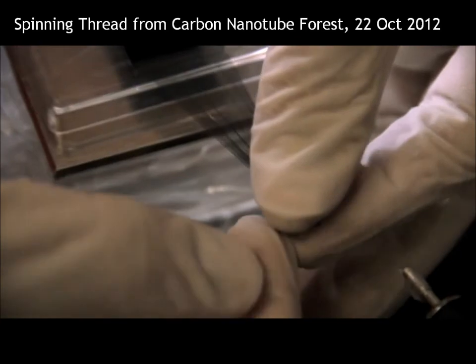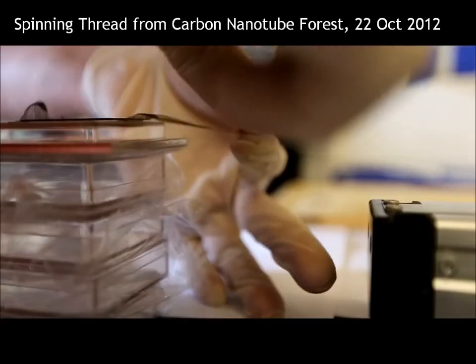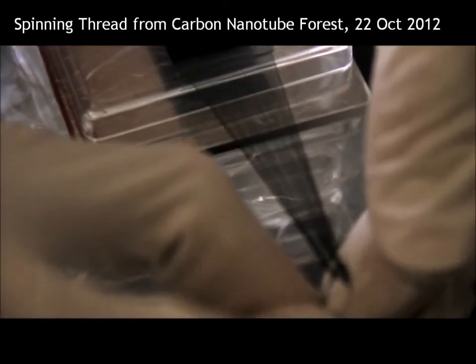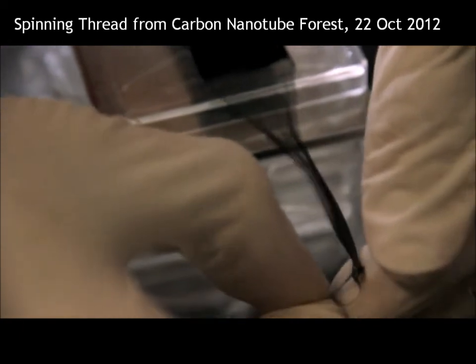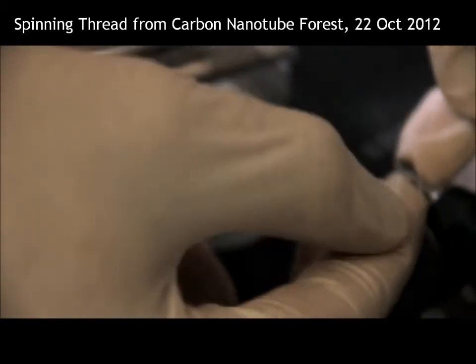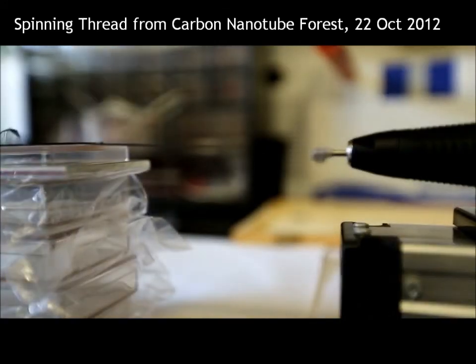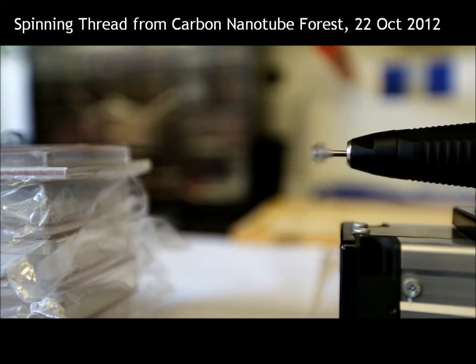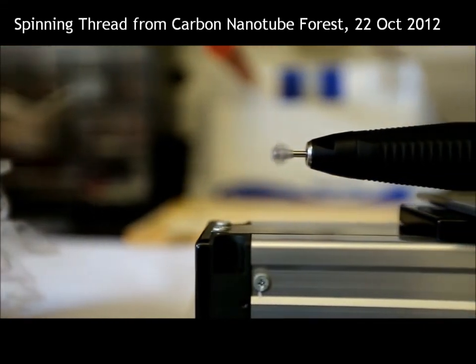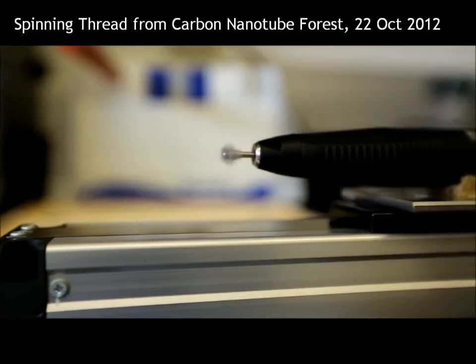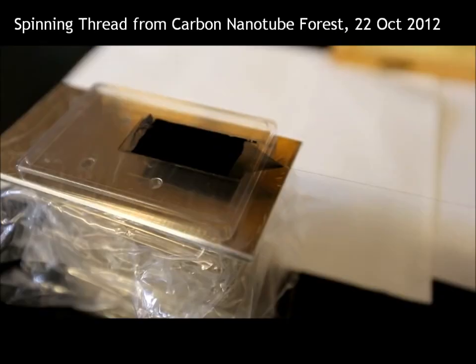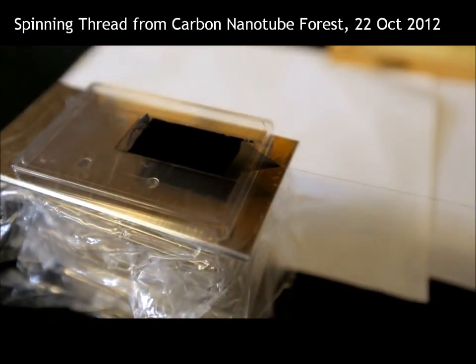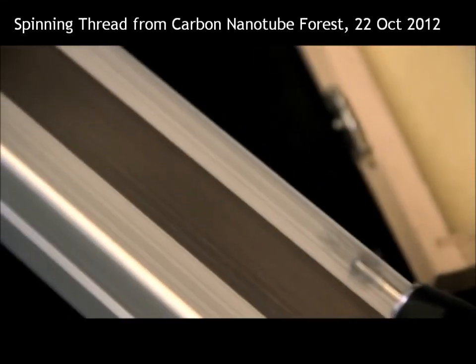That's what we'd like. So today my colleagues, Teddy Baker and Dr. Okada, will be showing us how we spin carbon nanotubes in the lab. Teddy's attaching a web of carbon nanotubes that he's pulling off this carbon nanotube forest, and he's attaching it to a spinner using double-sided tape. You can see just how sticky carbon nanotubes can be and why they're really difficult to work with if we're talking about large-scale applications. As he twists the device and pulls away, the web spins together, and what we get is a carbon nanotube yarn. As the carbon nanotubes pull off the forest, they come off almost like a sweater unraveling, pulling off the next carbon nanotube. So even though they're nanoscale, we can get a macro-scale yarn out of these materials.